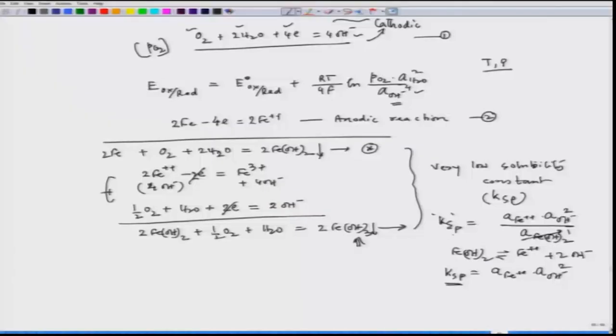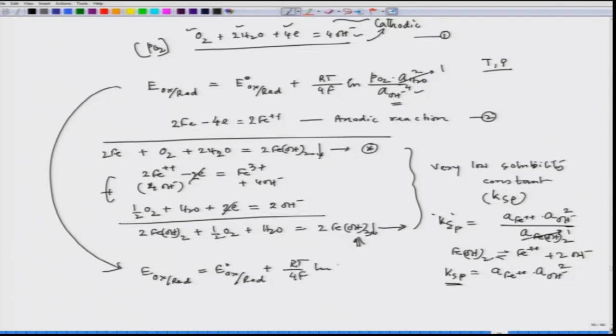And since they have a very low solubility product, we can say that they are practically insoluble. So the activity of OH minus we can consider to be fixed in this particular situation. And the activity of H2O, if it is pure, can also be considered as 1. So now the entire equation boils down to this reaction, plus RT by 4F ln PO2, the partial pressure of oxygen.